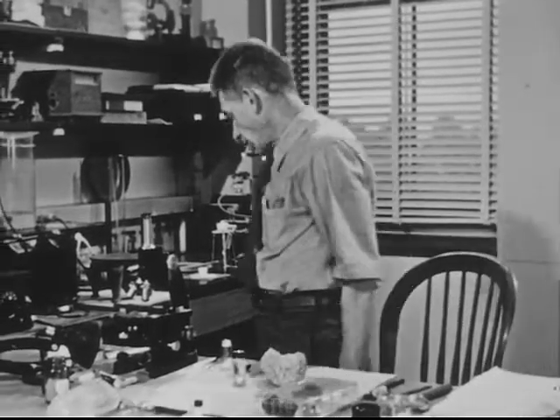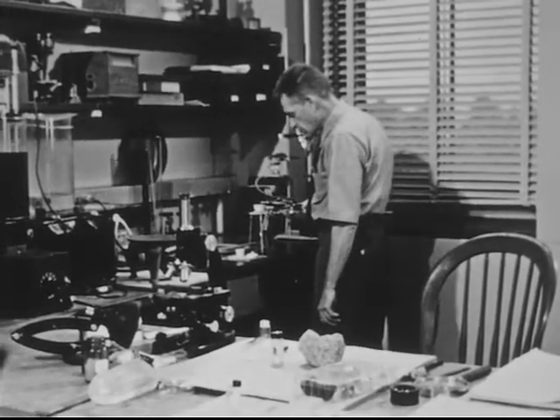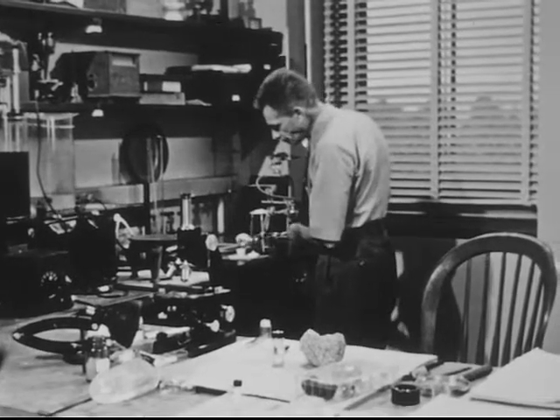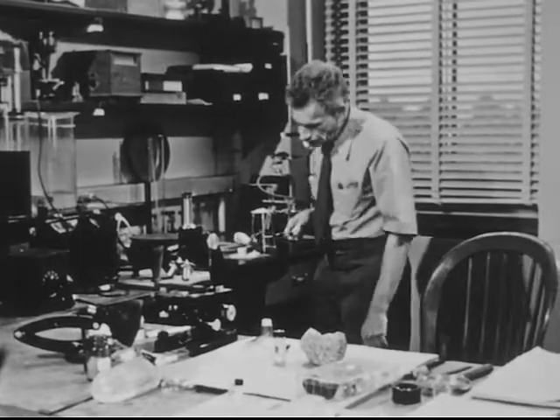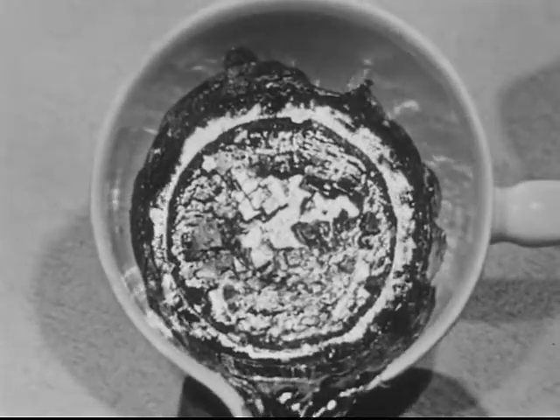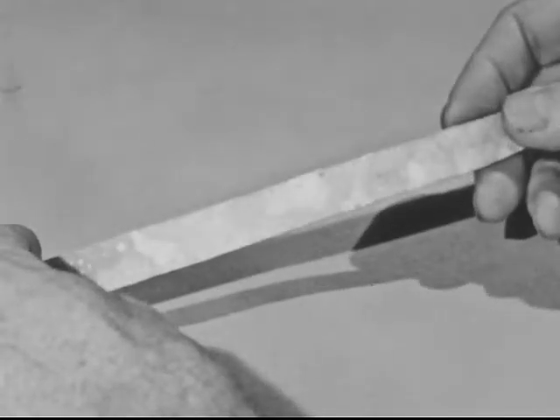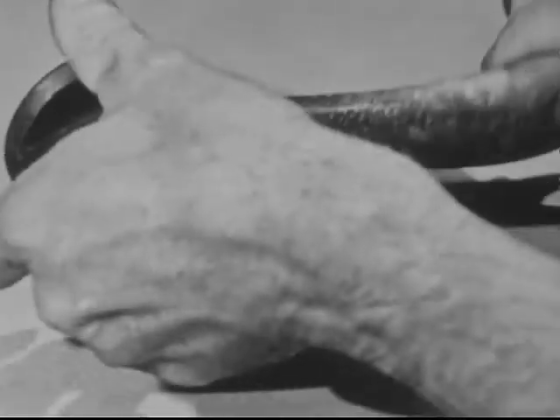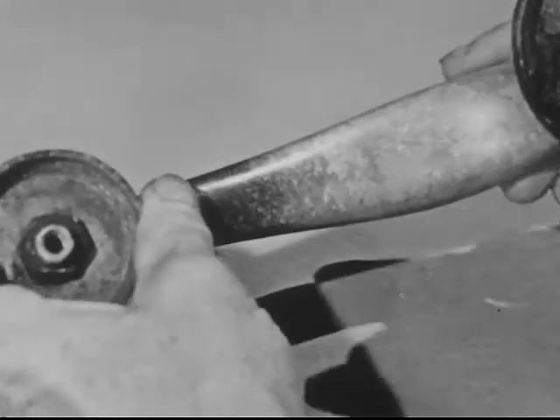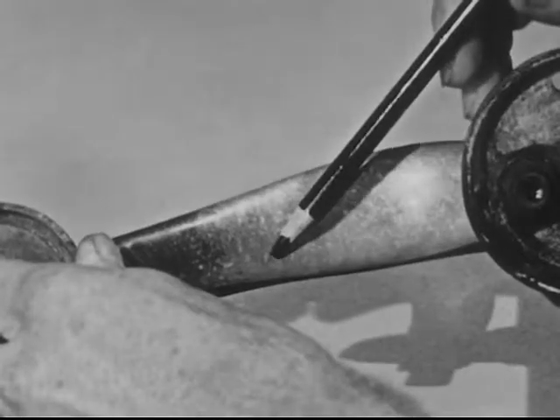When you came in, I was melting some bismuth in a crucible over here, and it's been cooling. Crystals ought to have formed on the sides of the crucible, so that when I pour off the part of the bismuth that's still melted, you can see them. Sometimes you can show up the crystals in a finished piece of metal by polishing the surface and then etching it carefully with something that will eat away the metal. Here's a cast brass door handle which the manufacturer polished, and then over the years the sweat on people's hands etched it. Now you can see the boundaries between some of the crystals which make up that door handle. In most pieces of metal the crystals are much smaller because they've been broken up when the metal was drawn, rolled, or hammered into shape. But the metal is crystalline just the same.